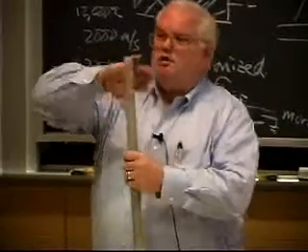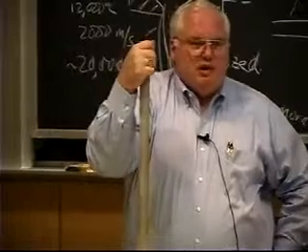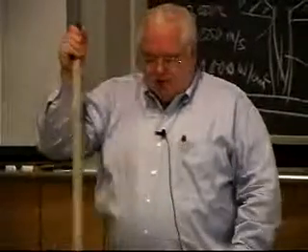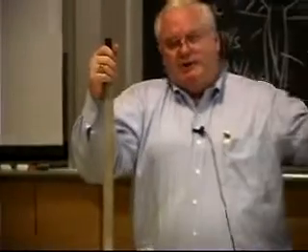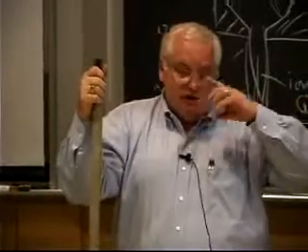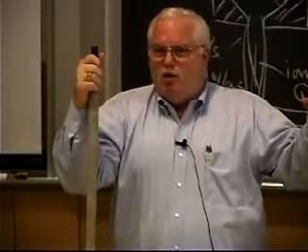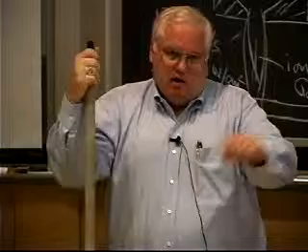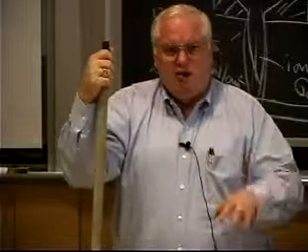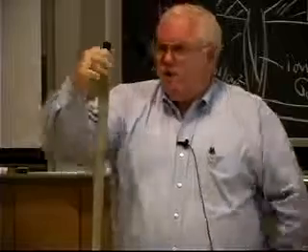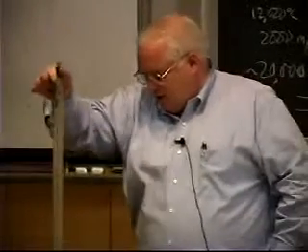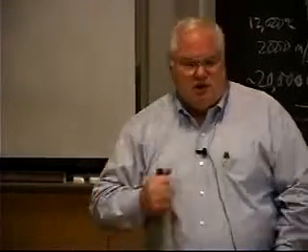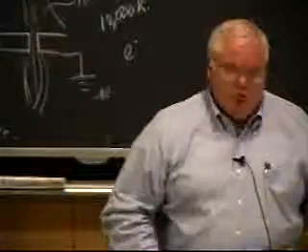This one is about a 2,000 amp unit, and a human cannot operate this one. Basically, it gets clamped into a machine, and it's made by the Weld Mold Corporation. If you go into a steel plant where they make big ingots of steel or other metals, these ingots might have 10-inch thick walls, a great big piece of cast iron. Those things crack sometimes, so they have some guy go in there with an oxyacetylene torch. He gouges out a big space in between, and they set this up with a machine, crank in a couple of thousand amps, and just melt metal. They make a new piece of cast iron, or weld the two pieces together with lots of energy.